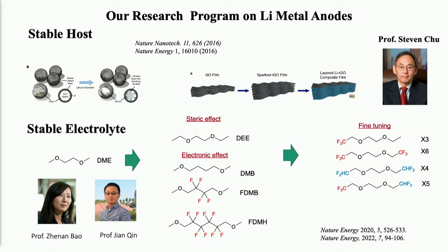But that's not sufficient. With Zhenan Bao and Jen, we have been designing stable electrolyte that can form a stable interfacial layer. We utilize the common concepts in organic chemistry, which Zhenan is an expert on: how do we build out the steric effect and electronic effect to make the molecule stable so it doesn't get consumed by lithium that much?